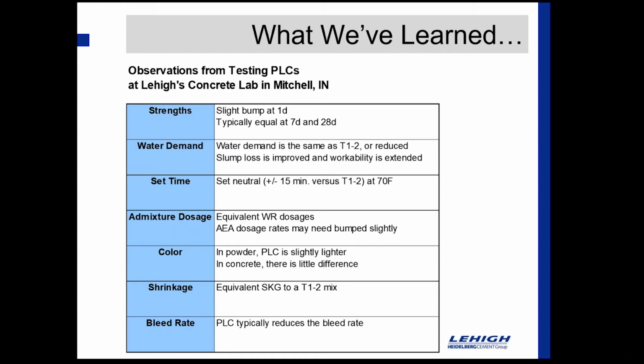What's been interesting, water demand is the same as type 1-2 or even reduced a bit. And we've seen slump loss improved in most cases, and workability is extended. We ran slump loss out to about an hour and saw that typically showed some value or some promise there with the PLC. Set time at 70 degrees has been neutral within about a plus or minus 15-minute window versus type 1-2 cements.